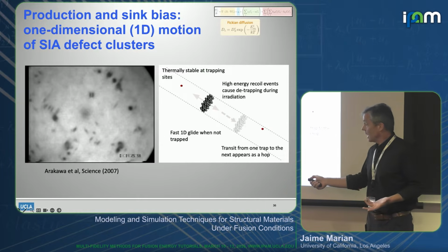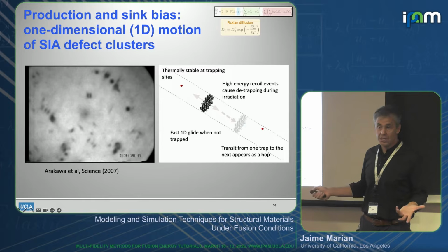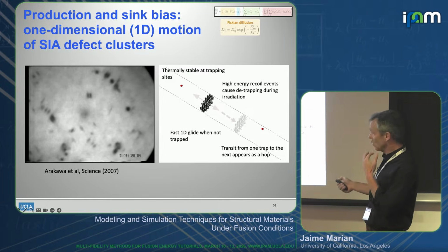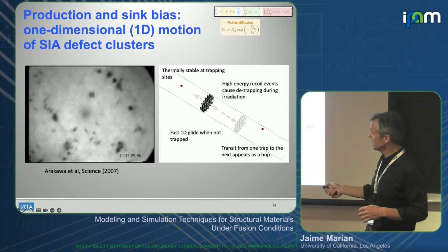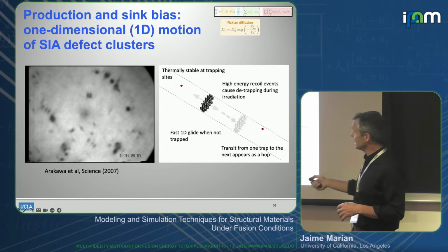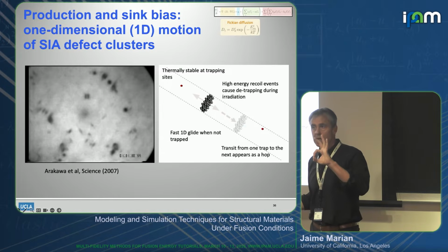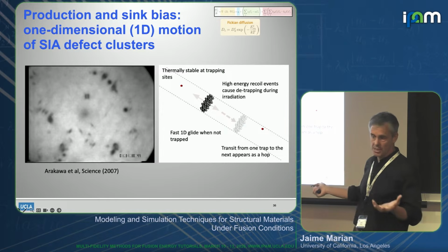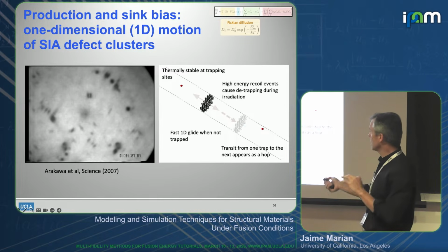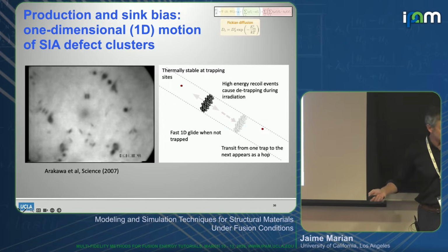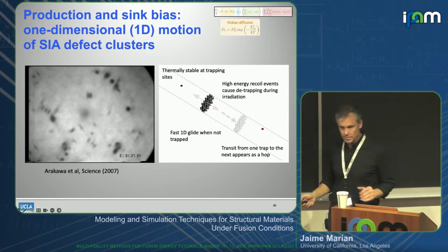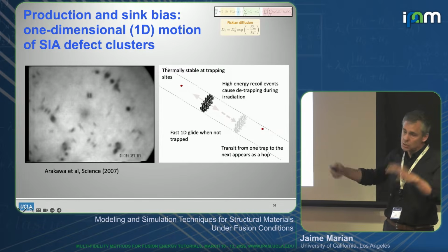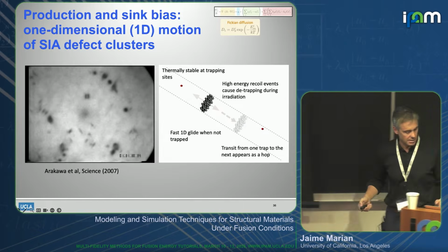So again, just understanding what's going on here is challenging because this determines the kinetics of the defects, how they interact with one another. So we've had very smart physicists help us interpret this. Now we know that these form disks, and these disks move preferentially along their glide cylinder, as we call it. They're trapped in their cylinder and they can move in 1 dimension like that. But some others don't form disks. They form these other more quasi 3-dimensional structures and they can't move. So we have to take all this into account in the models to be able to faithfully simulate what's going on.